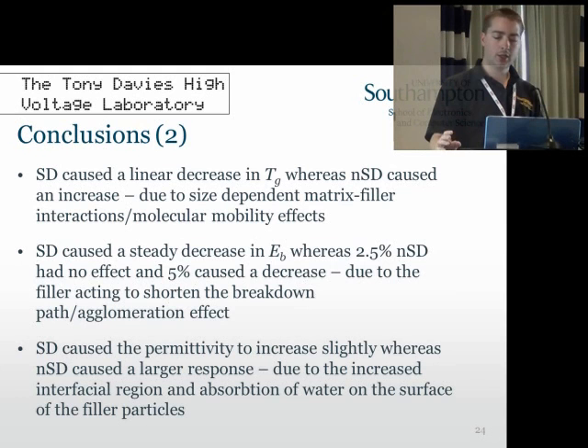When we looked at the electrical breakdown strength, we saw a steady decrease with the micro filler, whereas with the nano we saw that we could add up to 2.5% by weight without having a negative effect on the insulation properties. However, once we got up to 5%, the very basic mixing methods that we were using aren't sufficient to stop the agglomeration of the filler, so it's therefore behaving more like a microsystem and breaking down at a lower voltage.